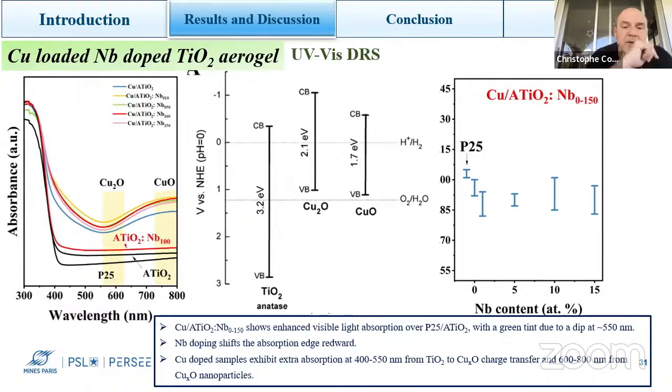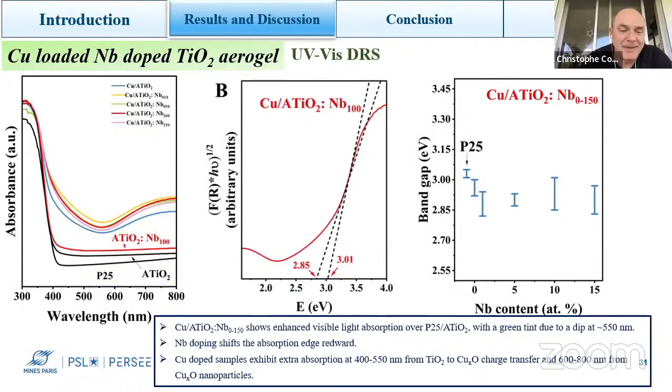Okay. Yeah, I just wanted to mention that I would avoid the Kubelka-Munk calculation in this case. Maybe it's risky to say it. Yeah, more than risky. I think it's not true. Okay. Because you can show this absorption, but the assumption of the Kubelka-Munk calculation is only with one band gap. So I think it's more than risky. It's false. Yes. Okay.